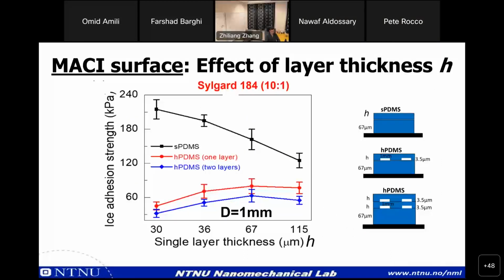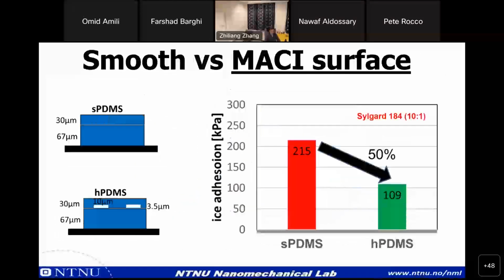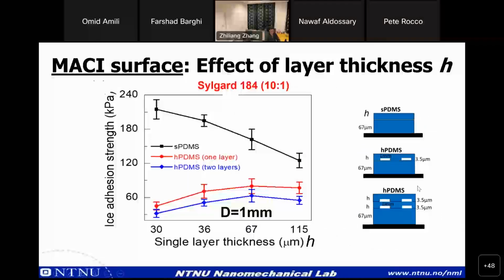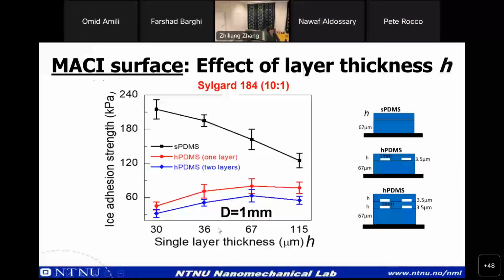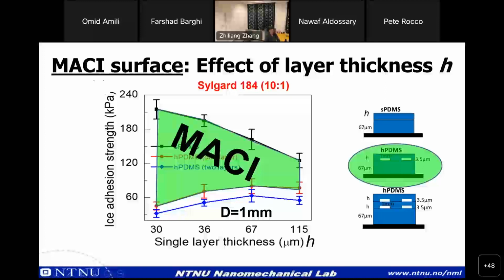So here is an overview of the MACI effect. So we change the H. H is the height of the top layer. So we change from 30 micron to 115 micron. The MACI mechanism has a huge effect. This is for single layer, and double layer is even more significant.